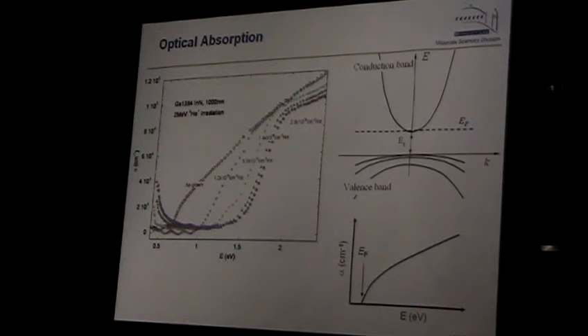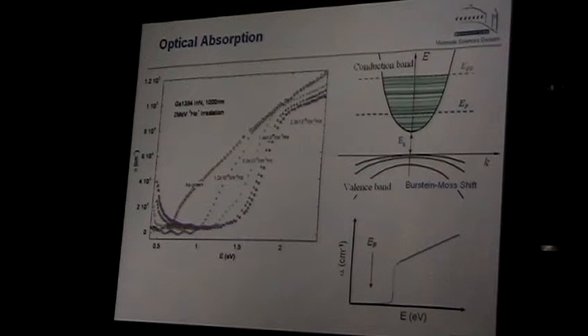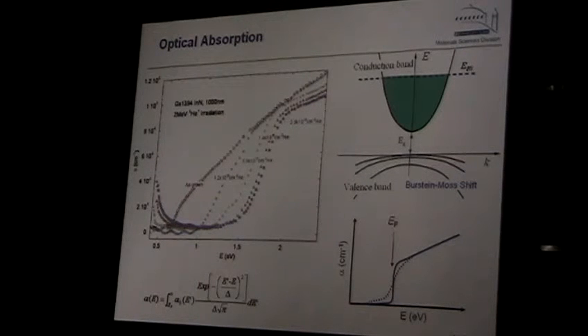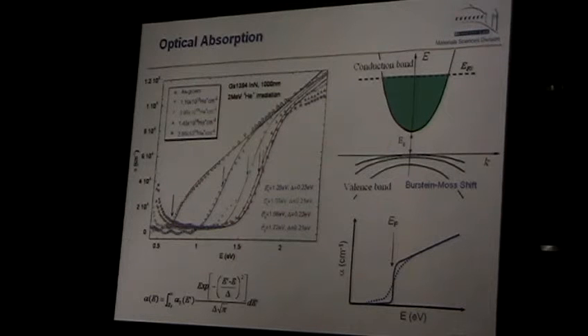And the way it works in this case looks like this. When we irradiate, we produce these defects, the electrons, and the Fermi energy goes up. So the lowest energy transition now is not this low 0.7, but only from here to the Fermi energy, because this is an unoccupied state. So this is almost 1.7 electron volts or something like that. And that's really what people were confused about, because they always have samples with high electron concentration, and they thought it was really the band edge, and this is the gap of the semiconductor. In fact, they were looking at the Fermi energy. This is the so-called Burstein-Moss shift that produces the change. And after you can model it, you get a good explanation of how it behaves.